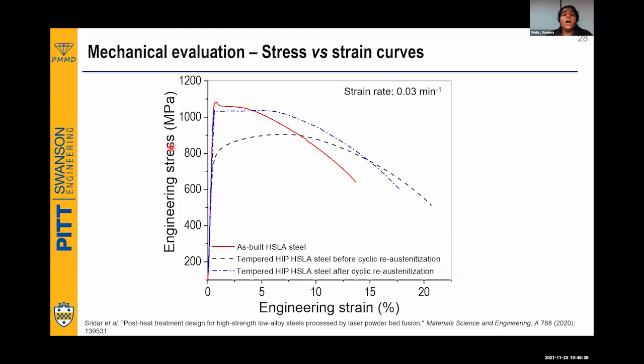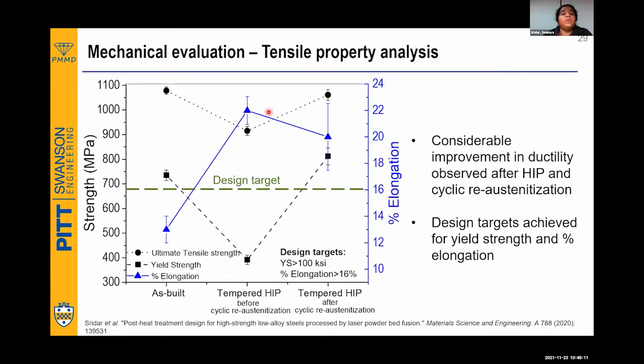and we need to do the tensile testing. So, the stress-strain curve. These tests were performed at a strain rate of 0.03 per minute. Yes, the as-built steel has a pretty bad ductility. But the tempered HIP HSLA after cyclic reaustenization has a very good ductility. Sorry, before cyclic. So that has a very good ductility. So let's look into the actual values.